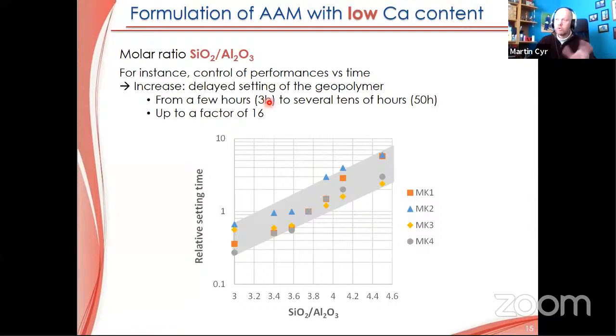For example, we are able to manage the setting time at 3 hours. And if we need to postpone this setting time, we can do it by controlling at least this ratio, up to several tens of hours. Sometimes we can reach also more than 50 hours with that. It could be very useful in some applications. So there is a factor up to 16. At least by changing this ratio, it's a way to manage the setting time. So it's very useful for that.